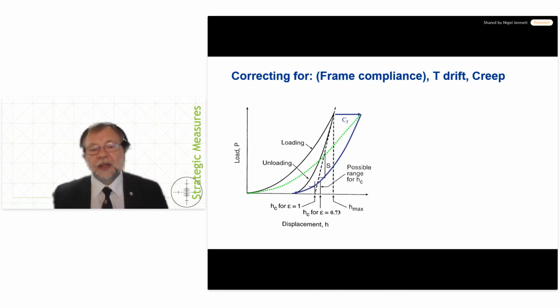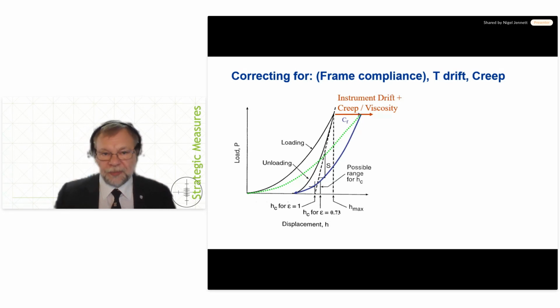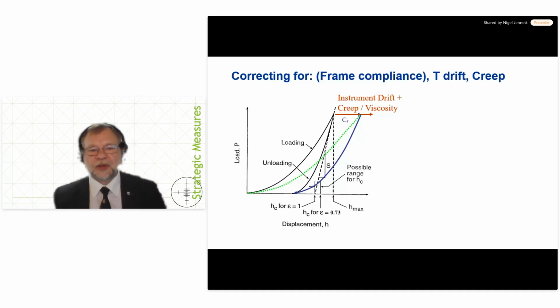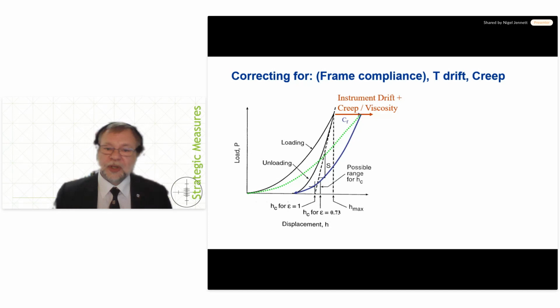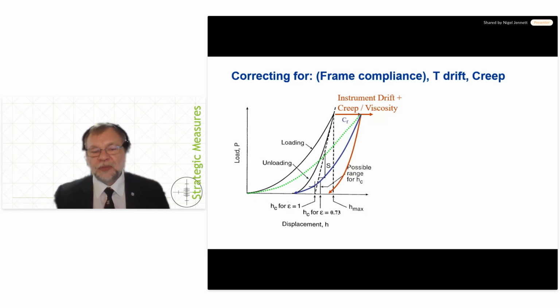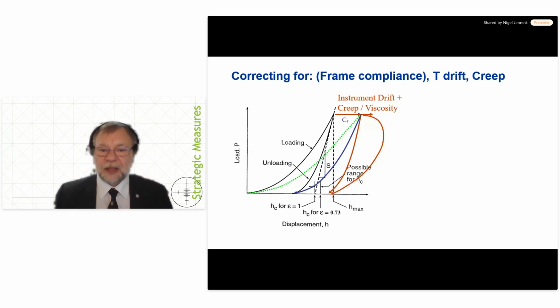The killers are thermal drift and indentation creep, or viscosity. And we'll talk about it in terms of drift and creep today. So what does that do? Well, at a constant force, it increases the measured displacement, which suggests that you have a bigger hole, which suggests that the elastic modulus is changing and the hardness is changing, even though you haven't done anything. Well, that's not right. If you take the force away, you still retain that drifted displacement value, so there has to be a correction. And typically you measure the drift rate and you correct it at room temperature by using various hold mechanisms. In the worst case scenario, you have a creep rate as you unload which is so high that you're creeping faster than you're unloading.